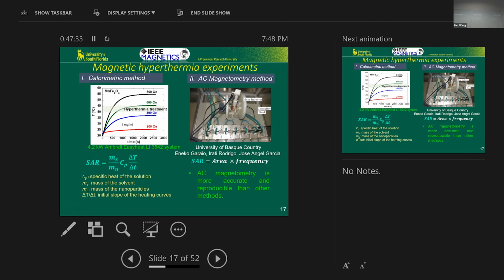So our data looks like this. This is for manganese ferrite spherical nanoparticles. We've looked at many different kinds of magnetic oxides. You can see that it's a function of time. You're plotting the temperature here in Celsius, of course. This is a fixed frequency, 325 kilohertz, and these are the applied peak amplitudes. From looking at it, you see that there's a slope. We need to maximize it so that we can get to this temperature. And then we need to saturate right in that window, the magic window of 40 to 45 degrees Celsius. So just by tweaking the parameters for specific particles, we can find the ideal condition for getting the saturation right at the temperature. You don't need to overheat it. You don't need higher power than necessary. And of course, if you don't apply the right amplitude, you will never heat it. And this saturation is a standard thermoequilibrium process to the environment.